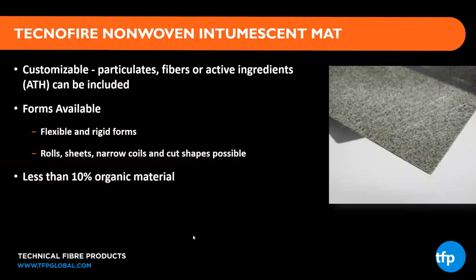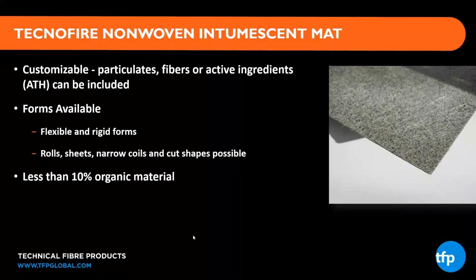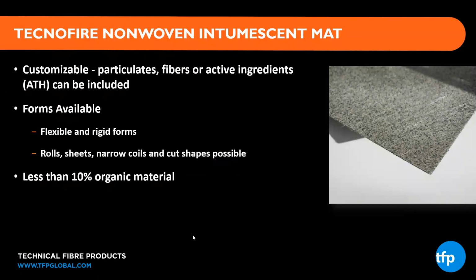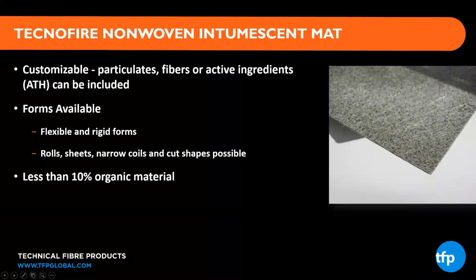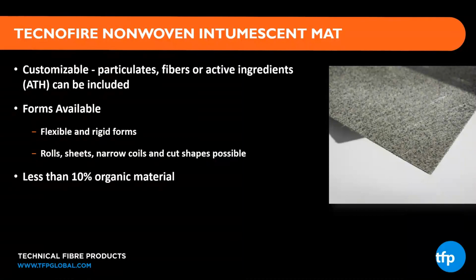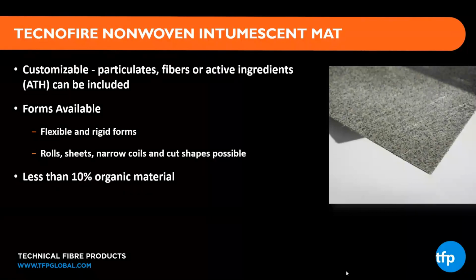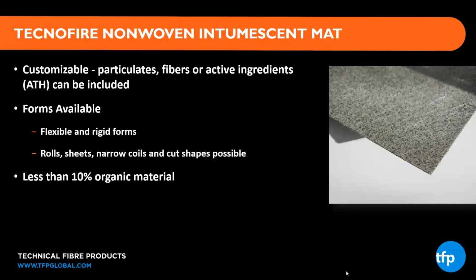We offer the rolled fabric on a 50-inch maximum width. The length of that can differ depending on which weight or which thickness you choose. We can cut these into sheets or even shapes. We offer this in narrow coils, so 50 inches is max, but we could also give you down to quarter or half-inch wide roll. The idea behind an intumescent is to have a product that does create that false wall, that char layer, once it expands.